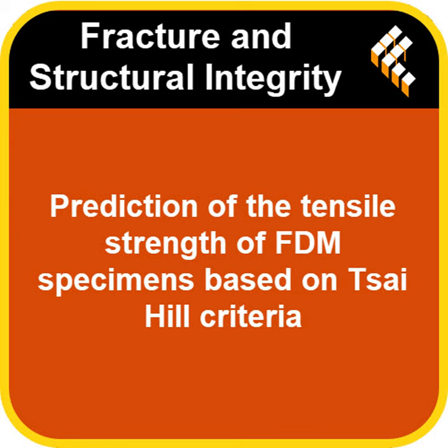Any ideas? The researchers suggested a reason for that slightly higher error in the contoured specimens. They think it might be because that outer contour shell itself has its own filament orientation, right? Yeah, it's printed too. And where they performed the shear test, which is one of the inputs for the Tsai Hill model, the orientation of the filaments in the shell might be slightly different from the main internal 45-degree structure in that specific shear zone. So the shell adds a little complexity that the basic model doesn't perfectly capture for that specific input. That seems to be the hypothesis.